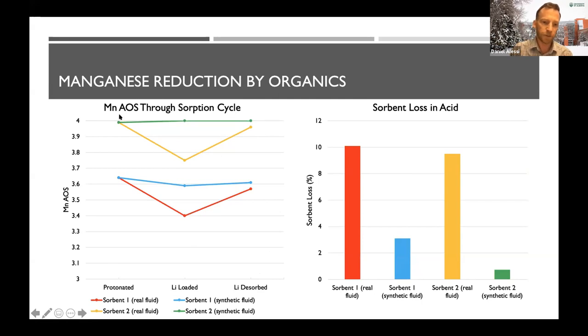And I'm not going to talk about this one, but this sorbent here, remember I said manganese 4 sorbents work really well. So what this is plotted against is what's called the manganese average oxidation state. And you can see this particular sorbent here, the green dot, is one that we were highly successful at getting almost all manganese 4 into the structure. But what's interesting is when you look at the manganese valence state, the charge, in the brine itself, when it's being lithium loaded, this is in the solid material itself, it declines. It goes from 4 down to 3.75.